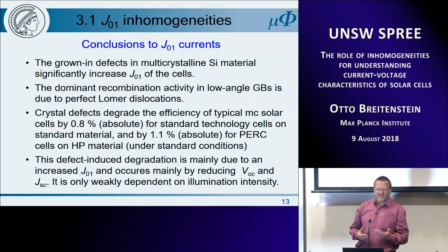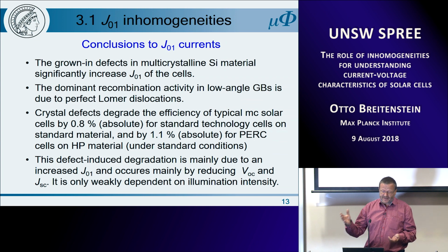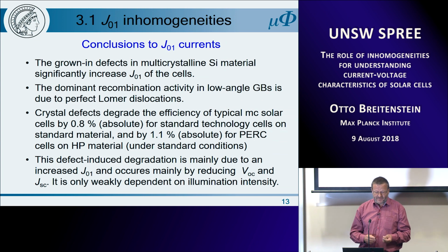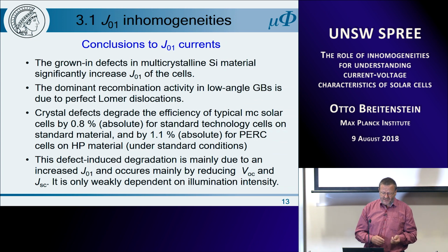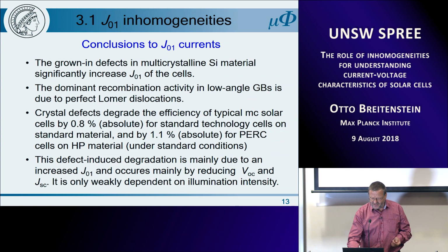So the dominant recombination activity is obviously due to these perfect Lomer dislocations, and these crystal defects degrade the efficiency in a typical multicrystalline cell by 0.8% and in the PERC cell by 1.1%, in spite of the fact that the PERC cell was on high performance material. And this defect-induced degradation is mainly due to an increased J01 and occurs mainly by reducing VOC and JSC. So this is only weakly dependent on the illumination intensity.